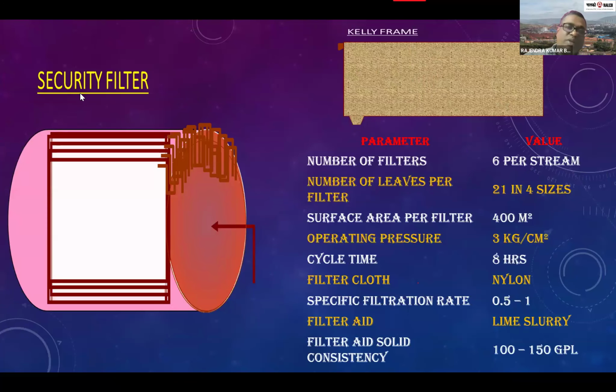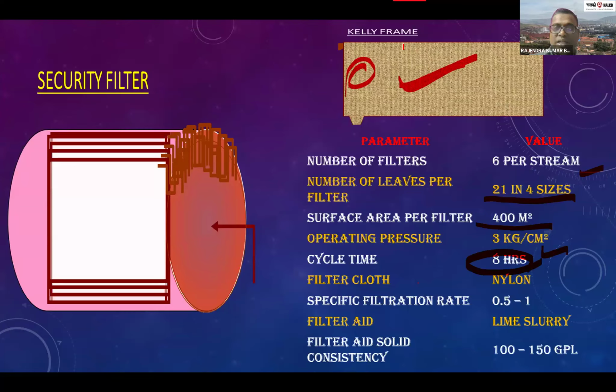The first is the security filter. Number of filters is 6 per stream, 21 in 4 sizes. Number of leaves, these are the leaves, 21 in 4 sizes. Surface area per filter is 400 meter square. Operating pressure is 3 kg per centimeter square. Cycle time 8 hours. The filter cloth, this yellow cloth you can see, is a nylon cloth. Specific filtrate rate is 0.5 to 1. Filter aid is lime slurry, and filter aid solid consistency is 100 to 150 gpl.